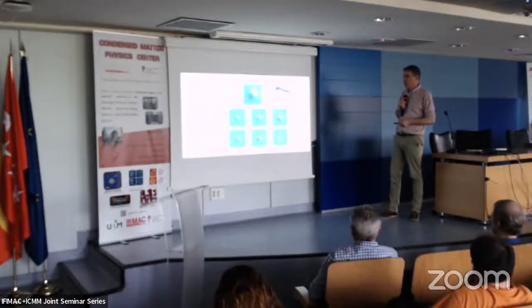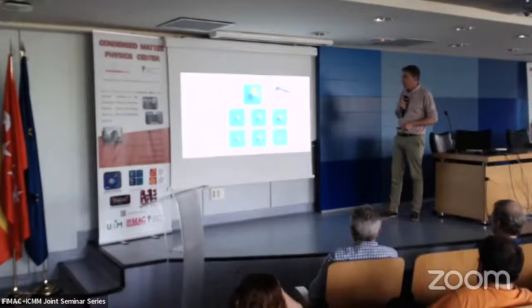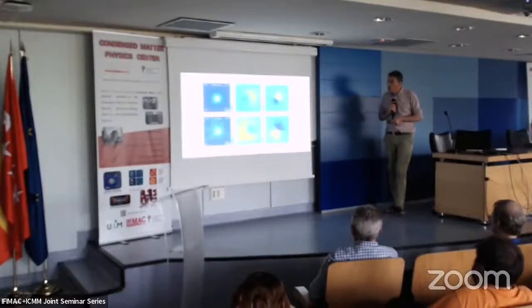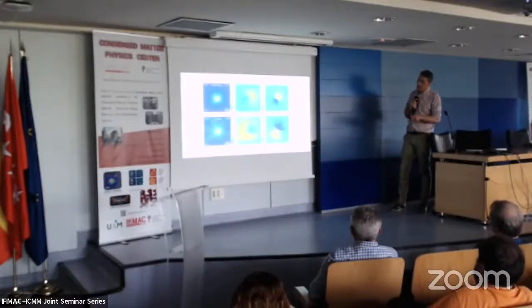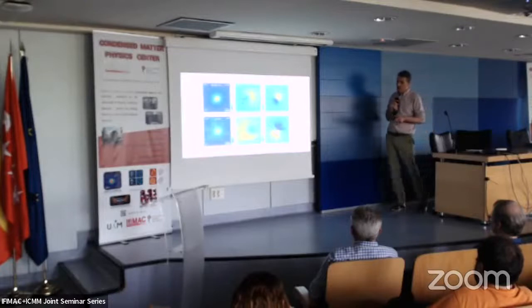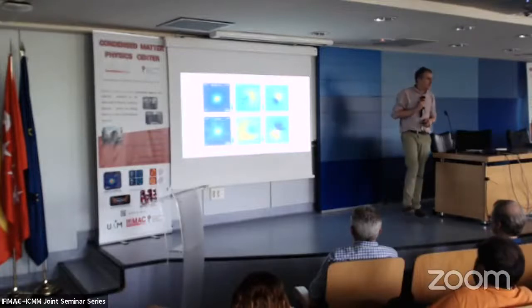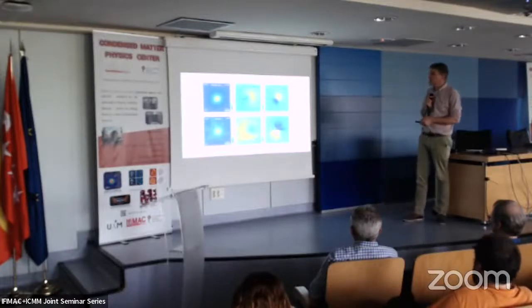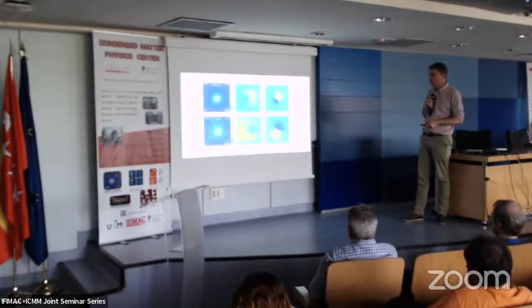further from the vortex core, and you see that the size of the signal decreases. If you have anisotropy, then you have different states. Now, what was very nice is that Moon and Alfredo made really a map of all the impurities which we found in our experiment, and they managed to calculate something which really looks, given the circumstances, very much like what we find in the experiment. Not just in a system which is isotropic, but also when you have a significant anisotropy.